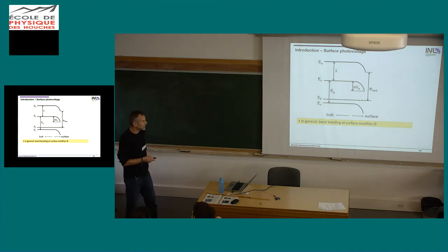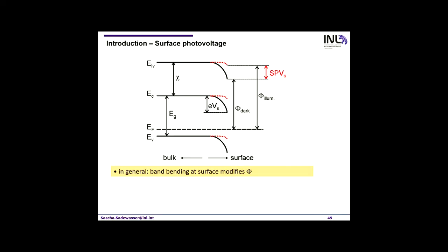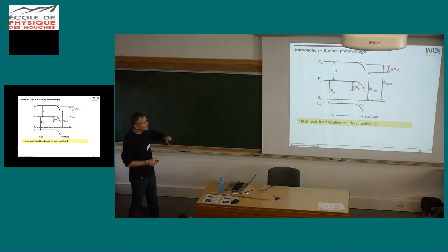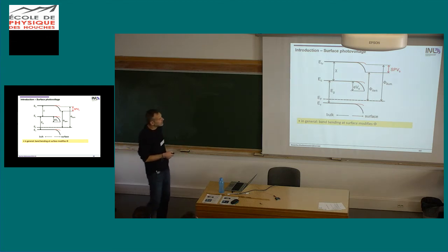And again, we measure this by measuring forces. So you can illuminate your sample, and what happens, you generate charges, and they can recharge these defect states. And normally what happens in most of the cases is that the bands get flatter or flat. So in this case, for p-type material, we would expect that the work function actually increases under illumination because this band bending is reduced.